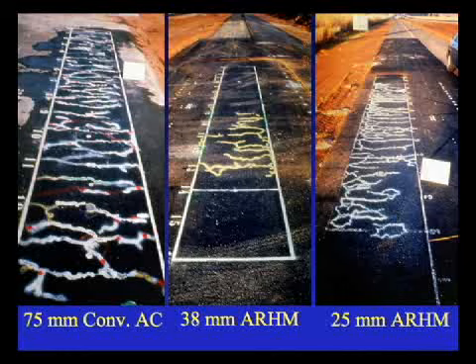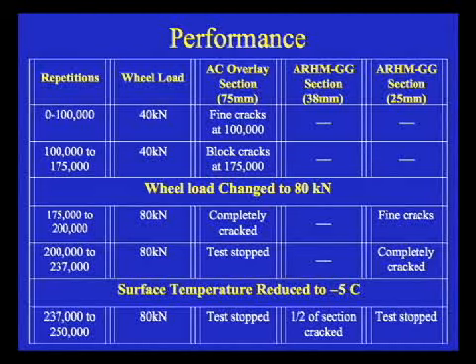This was the 75 millimeter conventional mix, the half thickness, 38 millimeters, and notice half of the section cracked. I'll explain that in a second. This was a 25 millimeter overlay, and it looks very similar to this, as you can see. So when this was designed, I told a lot of folks at Caltrans I thought the design guide was very conservative, and they laughed at me because they said, yeah, right, it's a 50% reduction, sure, and that's conservative. Well, this test and a lot of other actual projects in the field have verified that, but you can see the 3-to-1 here. This is basically what happened in the testing.